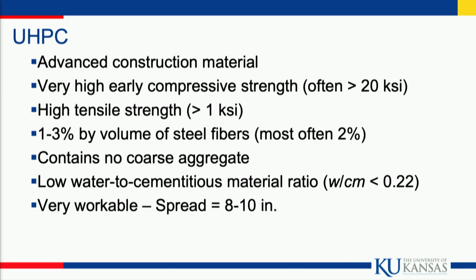UHPC is a very advanced construction material. It's a very fascinating material. It has very high strength, oftentimes greater than 20,000 psi, and high tensile strength, oftentimes greater than 1,000 psi. Typically, we use 2% steel fibers, which is kind of the high dollar item. It contains no coarse aggregate and has a low water-cementitious ratio, less than 0.22. This makes it pretty impervious, like we could use it in repair and the moisture can't penetrate it. So that's a fantastic property. Very workable, spread 8 to 10 inches, and I like to say it flows like molasses.